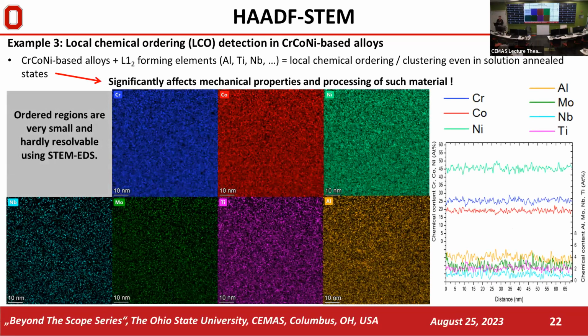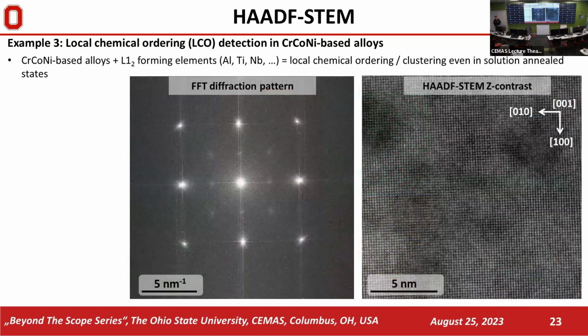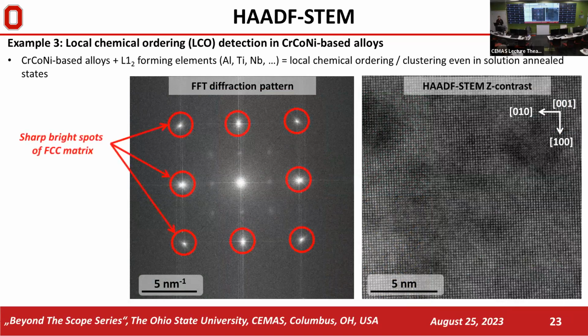This is an example of a chrome-cobalt-nickel based alloy with aluminum, titanium, and niobium. And if we do STEM EDS, these ordered regions are very small and hardly resolvable. So if you do a standard map, it's very difficult to see them. You would say that there's nothing present. Even using line scans or long scans, high signal scans, you cannot detect it. But if you simply use high-angle STEM, it can show you the presence of such ordering.